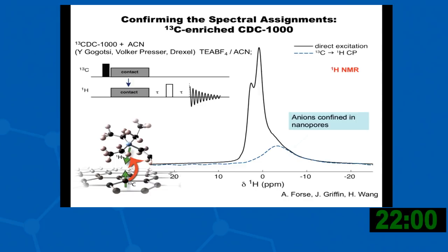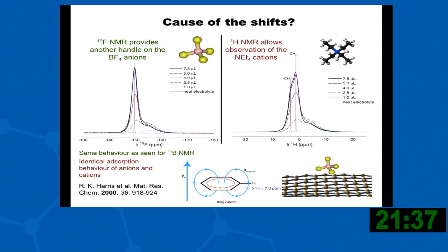We can prove that, and this is a collaboration of Yuri Gogotsky and Drexel, where he took some of his carbide-derived carbons and C13 enriched them, and then we can do a transfer magnetization from the C13 to the protons, and we only see the confined molecules or ions inside the pores, and we can clearly see a signature of the TEA plus cations. So where do the shifts come from?